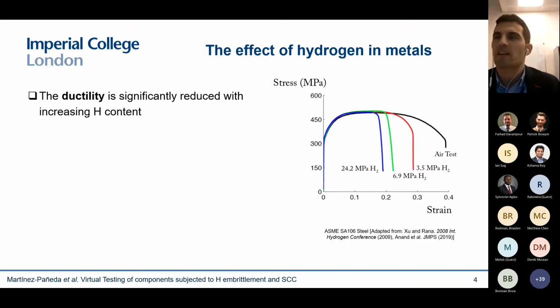So one of these effects is how the ductility of metals is reduced by the hydrogen content. You can see this here. These are uniaxial stress strain curves. And you can see that if you introduce hydrogen into your samples, for example, exposing them to hydrogen gas, you see a very dramatic reduction in the failure strain.